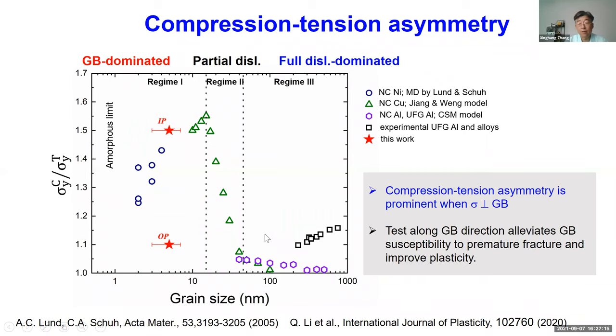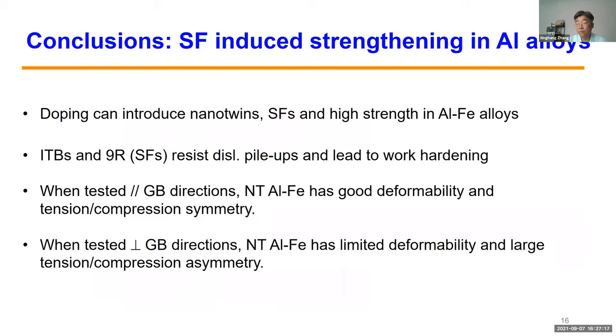All right, so that is the first topic I covered, briefly talking about how we can dope aluminum by adding solutes so we can introduce nanotwins. How can nanotwins or stacking faults improve the strength in aluminum iron alloy? And if we have these ITBs and 9R, they really block dislocations, introduce hardening, and then all this orientation and anisotropy gets into play.